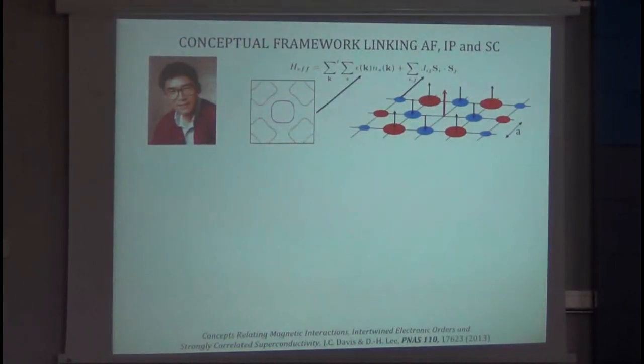It's got two terms in the Hamiltonian. This is like an undergraduate Hamiltonian. This term here is the delocalized electrons. There's their energy, and there's c dagger c, summed over spin and momentum for regions near the Fermi surface. That is like the Hamiltonian of any well-defined piece of metal. The specific thing is that we know the exact geometry of the Fermi surface. It isn't a model Hamiltonian, it's an exact Hamiltonian, because we know the geometry of the Fermi surface.